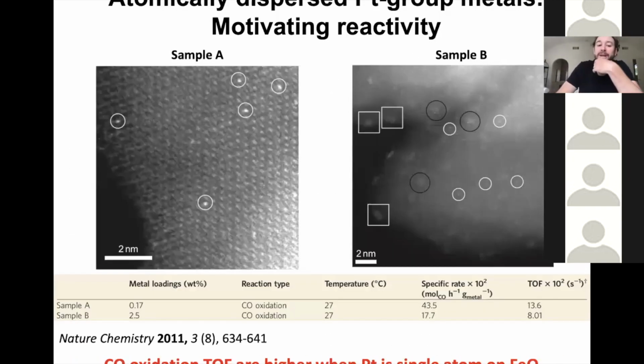About 10 years later, this was the paper from Tao Zhang's group that I think sparked a reemergence of interest in this area of so-called single atom catalysts or atomically dispersed catalysts. Here Tao Zhang's group was looking at platinum atoms on iron oxide, and they compared 2 samples. One sample where they said, we only have single platinum atoms showing up as these bright spots, and I'll talk about that more, in a TEM image on an iron oxide lattice. And in a sample B, you have some small clusters here.